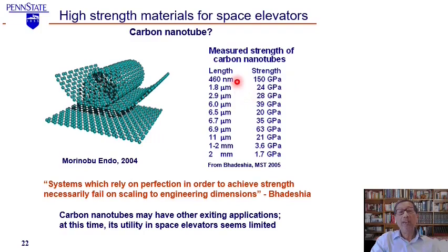But if you now go from nanometer to micrometer, you increase the size of this nanotube a little longer, up to about 1.8 micrometer. Micro is 10 to the power minus 6. So 1.8 into 10 to the power minus 6 meter as opposed to 460 into 10 to the power minus 9 meter. The strength drops precipitously from 150 gigapascal to only about 24 gigapascal.